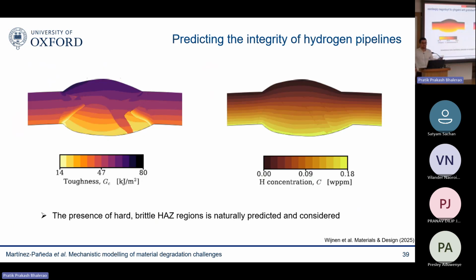And then what this basically allows us is to predict the variation in properties within your weld, within your macrostructure. You can see, for example, that this weld has a heat-affected zone here where the toughness is very low. So it's particularly susceptible to hydrogen. And that's a problem because people doing tests in their labs are testing base material, they're not testing the heat-affected zone, and this is of course what's going to fail first.